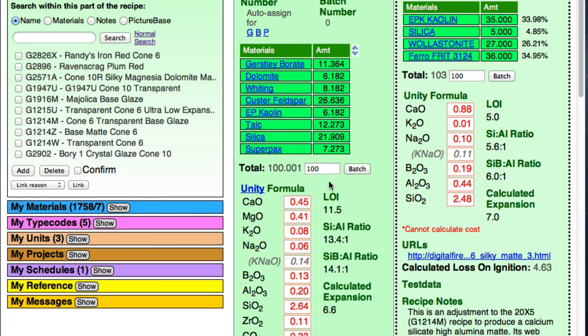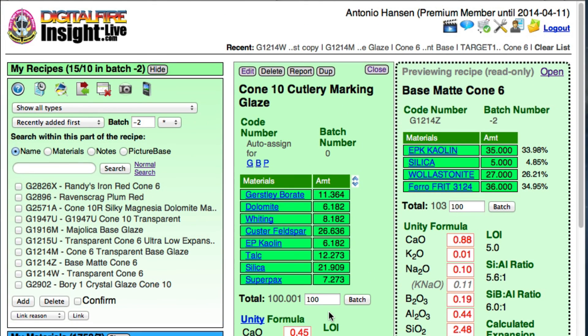Do you think this glaze would also be likely to leach? The answer is, of course, yes. The silica and alumina, and having things in the proper balance, are going to create a more stable glass, and a more stable glass is going to be less leachable. If they're not in balance, it's going to be less stable and therefore more leachable.